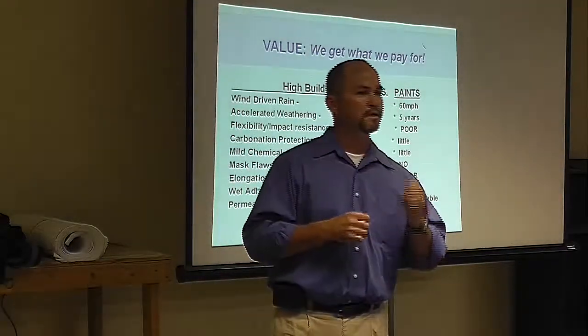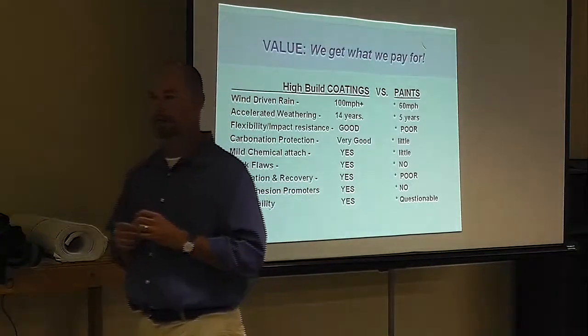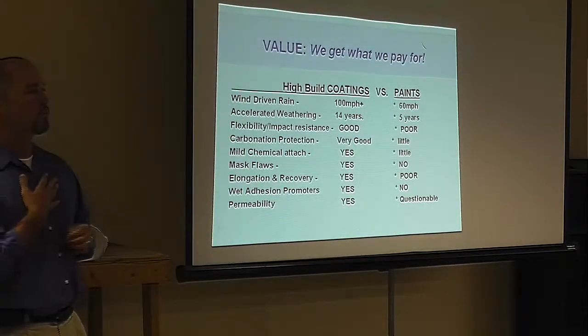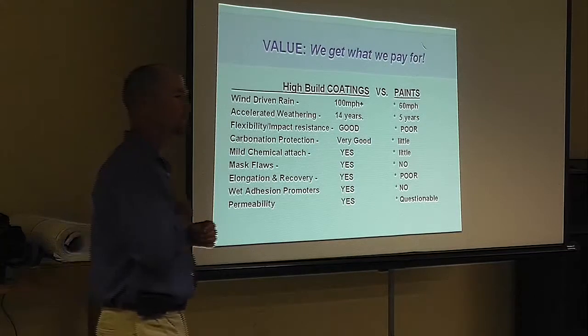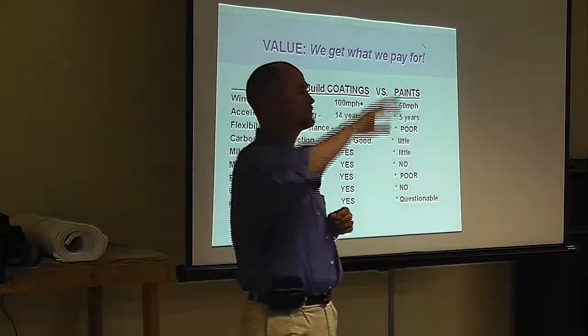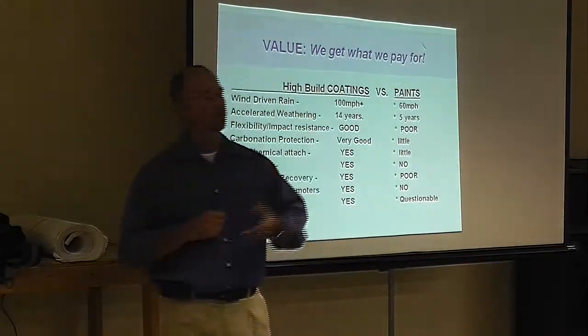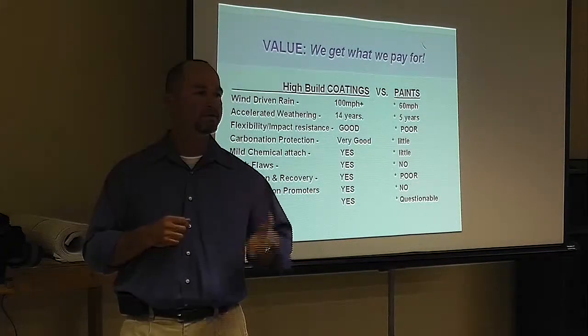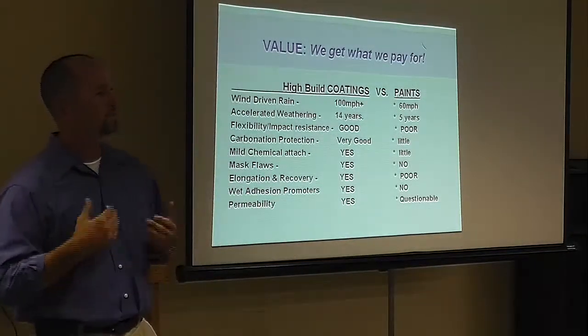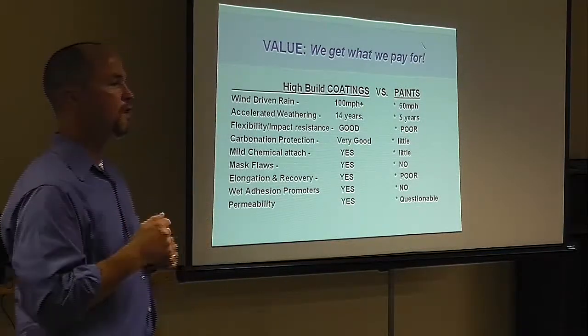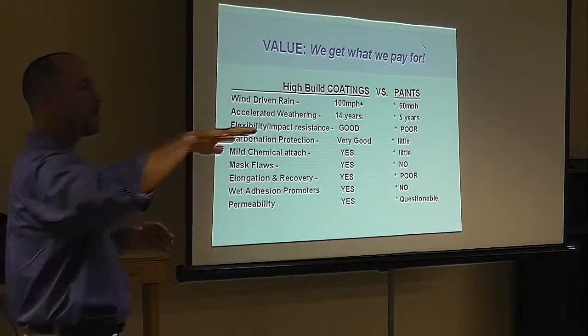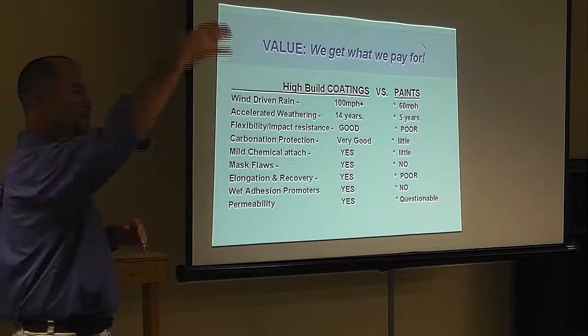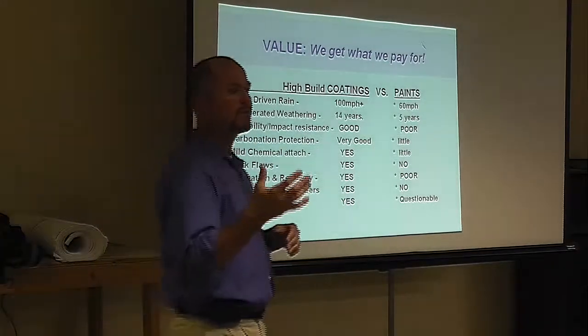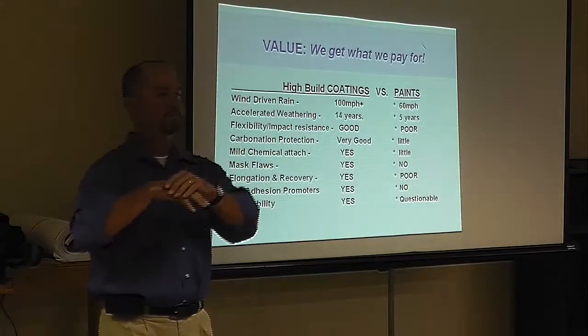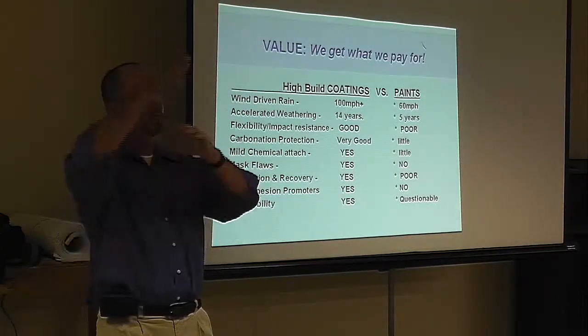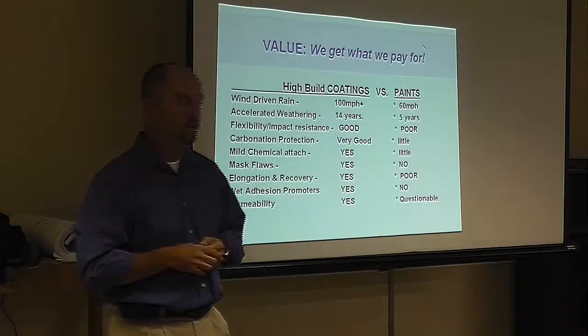And permeability. If you need a high perm coating, say for a parking garage: one of the projects I sold last year, I've got over 30,000 gallons on the Galleria parking garage. I had issues with the coating peeling years ago. I sold them one of our products with a high perm rating, coated it 6 years ago, and it still looks great to this day. So we've had no coating issues over there. Because when you have a garage and they want a light reflecting coating in there, water and rain is going to get in there somehow or another. So it's going to travel through that concrete. So you want a highly breathable coating so it doesn't push off. If you had a coating that wasn't breathable, you'd have blisters all around, pushing sheets of coating off.